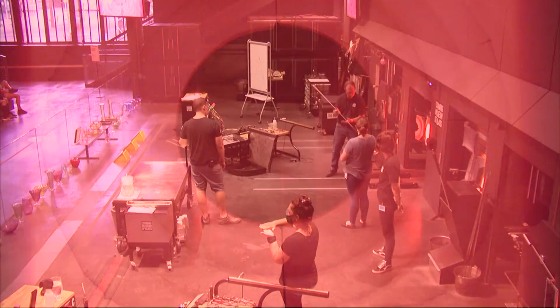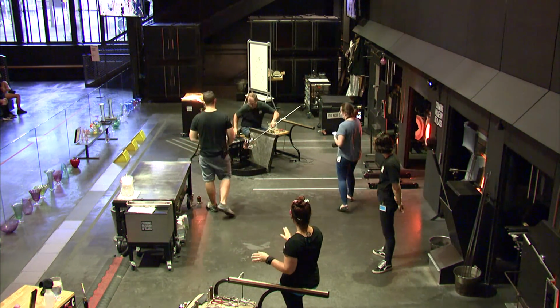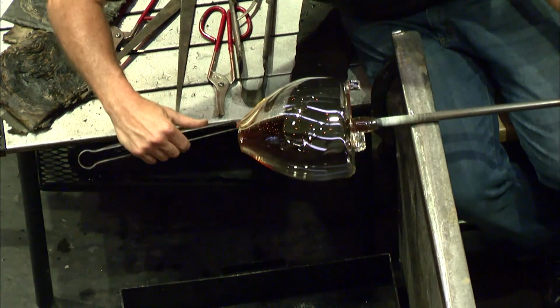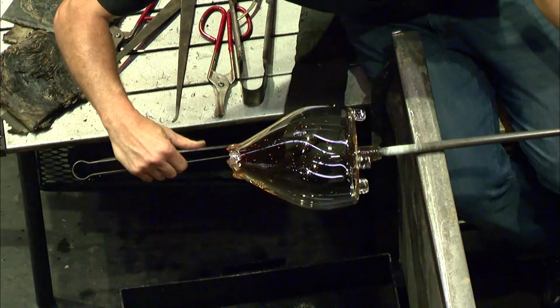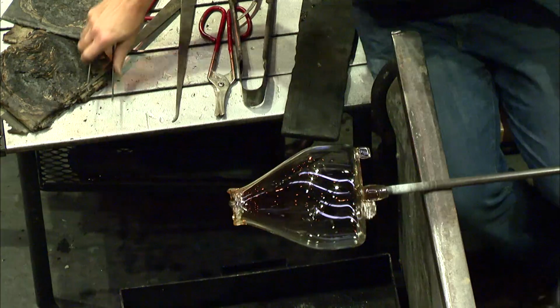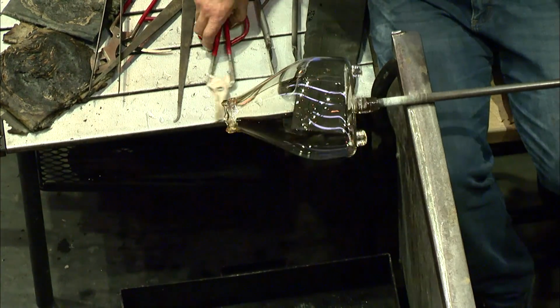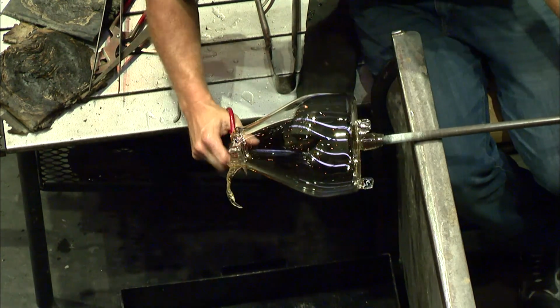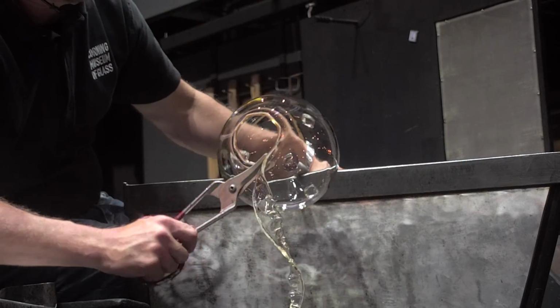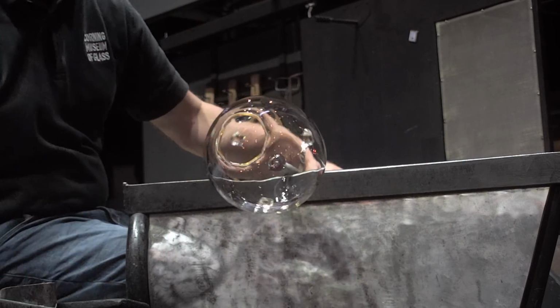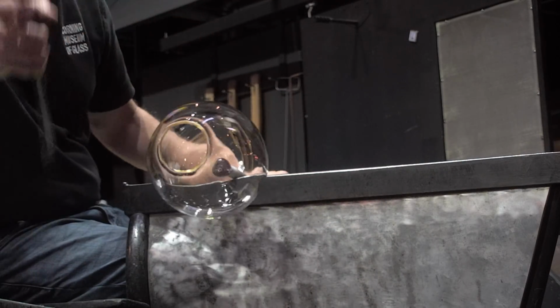So I mentioned that temperature control in glass making is really important, and for doing something like folding the lip over on itself, it's always really important. But Eric's going to set up the heat just right so that he's going to be able to roll that lip over onto itself, and it will adhere because hot glass will stick to other hot glass really easily. But if he heats the shoulders of this bowl too much, it'll actually start to cave in on itself. So managing the heat and getting the piece hot right where he wants to roll that lip over is really important. He might just use our reheating furnace to get that heat. He could also choose to use one of our torches to really localize that heat and warm the piece up in a specific area.